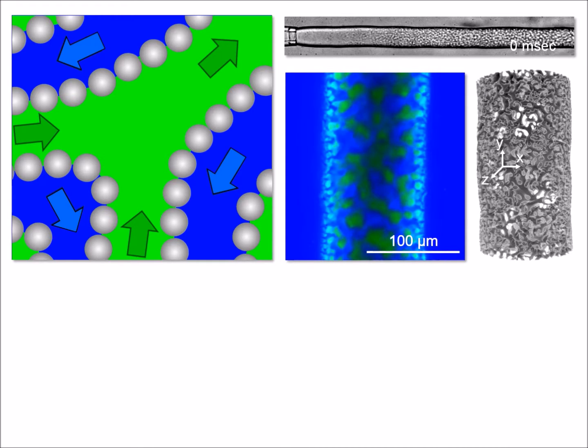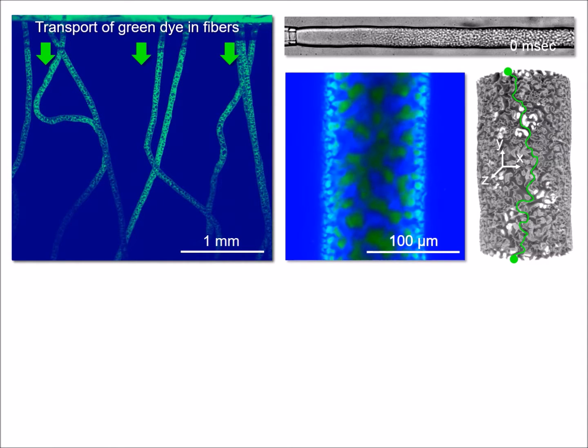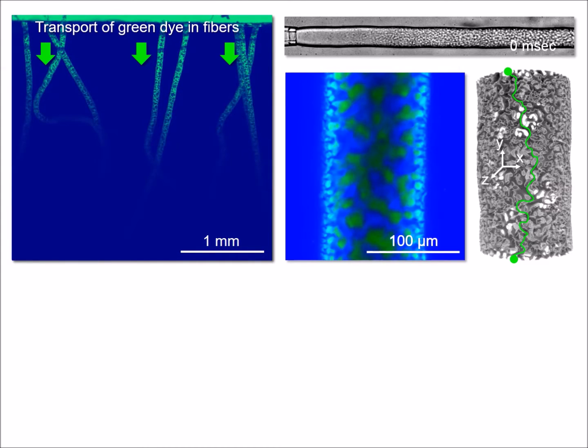The computer allows us to reconstruct their three-dimensional architecture. The structure tells us that oil molecules should be able to travel on a winding route from the top to the bottom of the fiber. And indeed, we could observe this transport process in our experiment as shown here. An oil-soluble dye travels throughout the fiber and colors all oil channels in green.